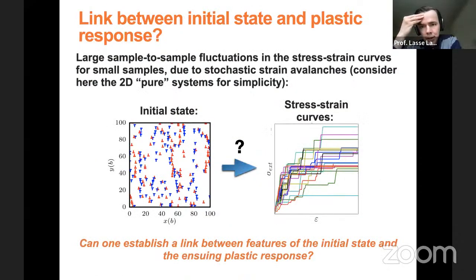So this is basically the problem statement here. So now you have this. Your simulations are basically started like this. You put a bunch of these dislocations in your 2D box, initially at random positions, then you let them relax in the absence of any external stresses, and you end up with a configuration that might look like this. So there's some structure there because the dislocations interact and they like to move to some energetically favorable configuration. But then when you apply stresses, you can then record a stress strain curve that might look like one of those curves here.